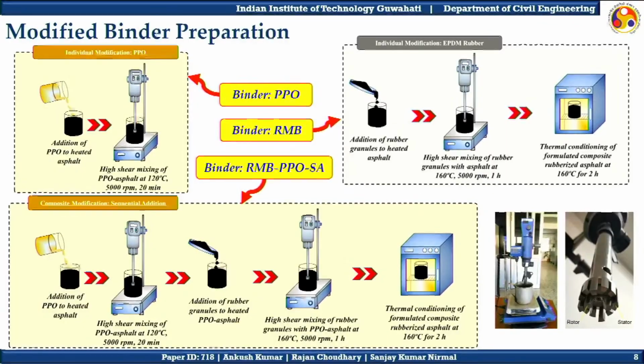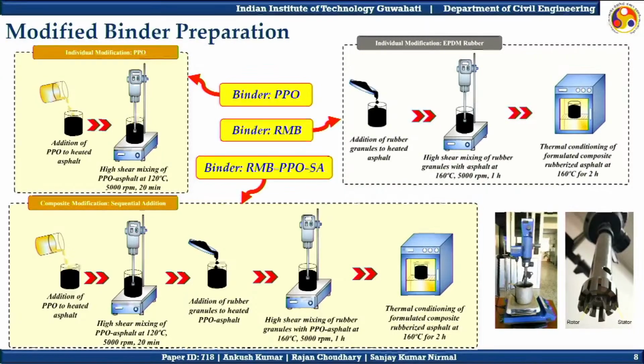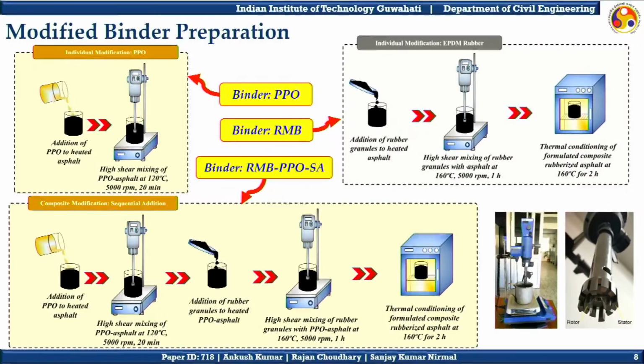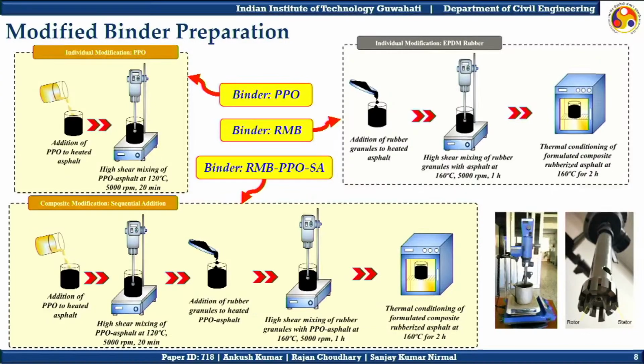So for binder modification, for individual modification with PPO, the respective dose of PPO was added to the base asphalt heated at 120 degrees Celsius and high shear mixed, and the prepared binder was termed PPO. While for the individual modification with EPDM rubber, the rubber granules were added to asphalt heated at 160 degrees Celsius with a shear mixer running at 5000 RPM for 1 hour, and the prepared mixture was thermally conditioned for 2 hours at 160 degrees Celsius. For composite modification using sequential addition, first of all, the PPO was added to the heated asphalt and then shear mixed. Thereafter, the EPDM rubber was mixed into the PPO added asphalt, and that combination was high shear mixed at 160 degrees Celsius for 1 hour. And thereafter, the whole mixture was thermally conditioned for 2 hours.